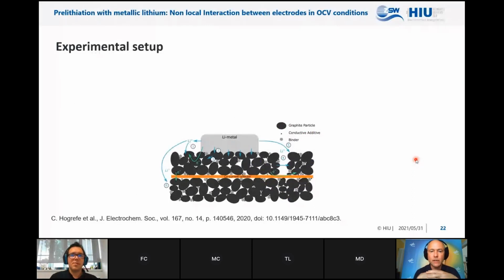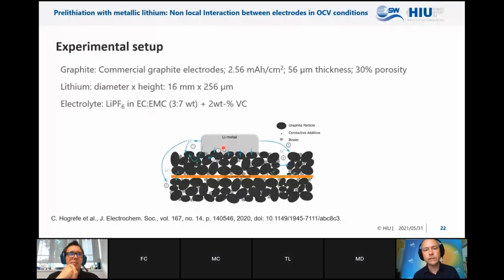So with our colleagues from ZSW, the group of Margret Wohlfahrt-Mehrens, they made a very interesting experiment. They studied a graphite electrode. They wanted to understand how pre-lithiation is influencing the behavior under open circuit potential conditions. So they implemented physically a plate of lithium on top of the graphite. Then they wrapped the full configuration in a separator, and they had a counter-electrode which was just lithium.